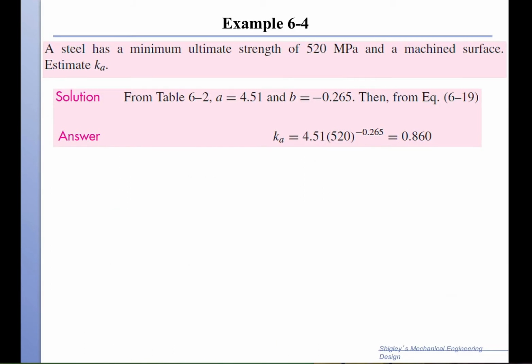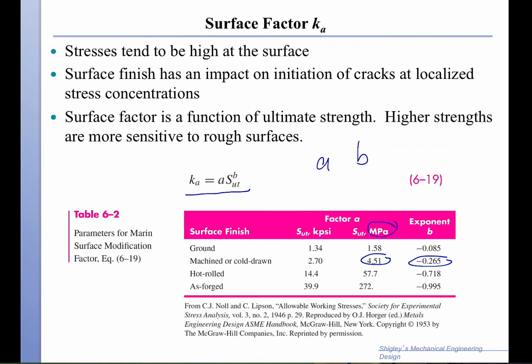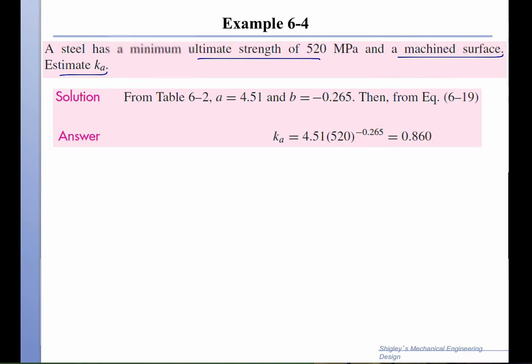For example, if we want a steel that has an ultimate strength of 520 and a machined surface, we want to estimate the surface factor. From the table, it's machined, so A is 4.51 and B is minus 0.265. You substitute here, and you get that the surface factor is essentially 0.86.